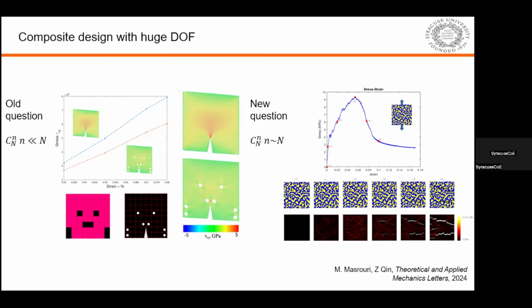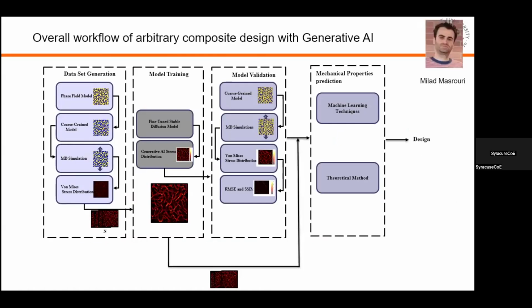So that's why one of the students in my group, Milad, he's here, we study the new research by studying the arbitrary composite with almost equal concentration of the rigid and soft material, and then solve that with the generative AI. So he used stable diffusion, which is much more powerful and generates effective, good visualized images than the DC GAN. This study started with some images that we obtained from molecular dynamics simulation for the stress distribution of this composite.